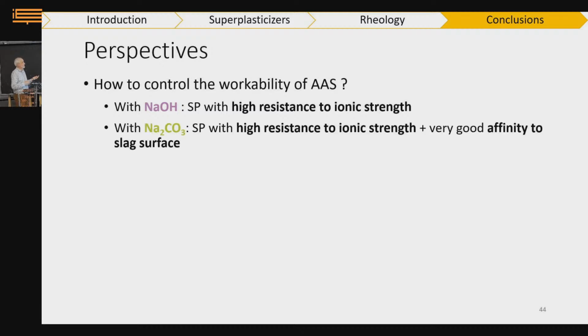How can we go against those effects that are relatively troublesome in terms of the workability of the paste? Well, we have seen that with sodium hydroxide, this is an issue of solvent quality. So we need to find polymers that have a high resistance to ionic strength. So we are working on it. We have some ideas. With sodium carbonate, we see that we have an issue also of adsorption. So we need to find a polymer that has a good resistance to ionic strength, but also a strong affinity for the slag surface.